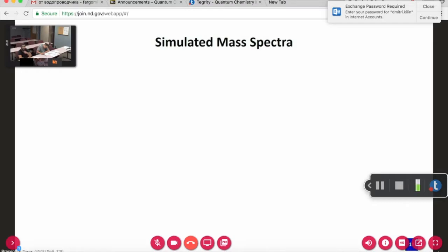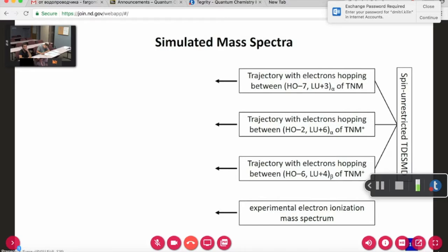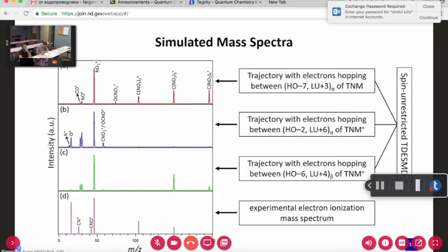So actually, we can extract the simulated mass spectrum from TDESMD simulations, and we can even compare with the experimental mass spectrum. Next, please. Yeah, as we can see here, the simulated mass spectrum has some similarity with the experimental electron ionization mass spectrum. The dominant peak is nitrogen dioxide. The red one is for the neutral system, and the blue and green ones are for charged species. As we can see, the parent ion for the neutral system is stronger, but for the charged species, it is much weaker. So this tells us the cation is much easier to fragment than the neutral system. Yeah, that's all. Okay, let's thank Yulun.